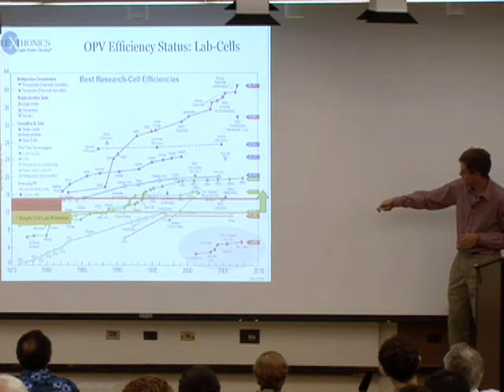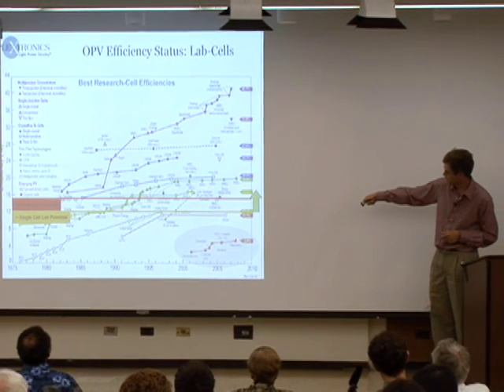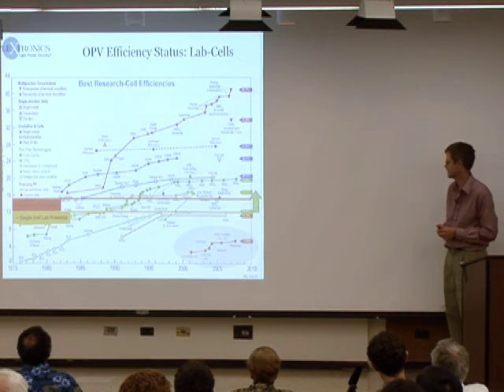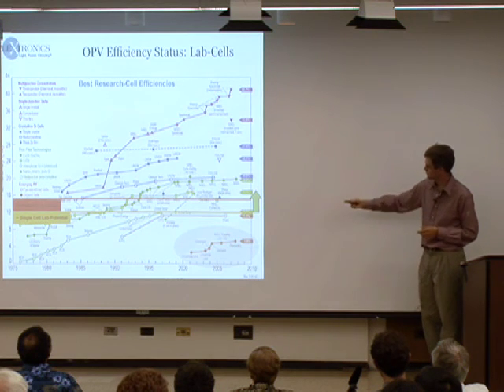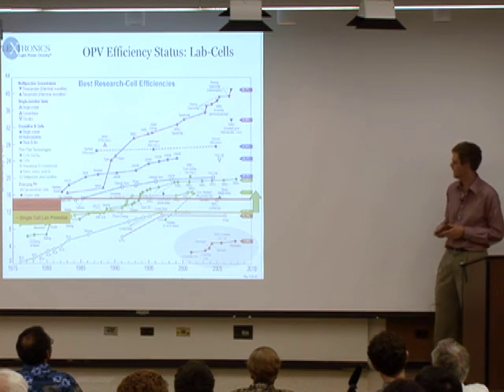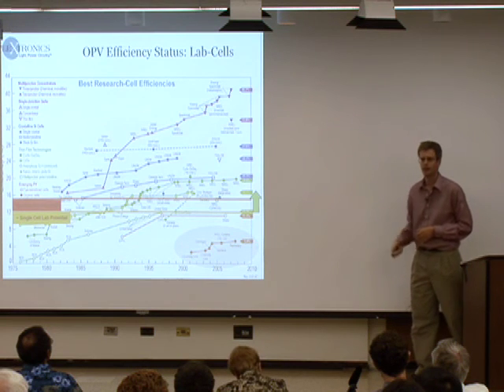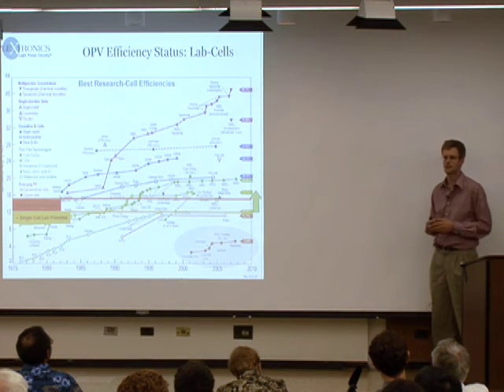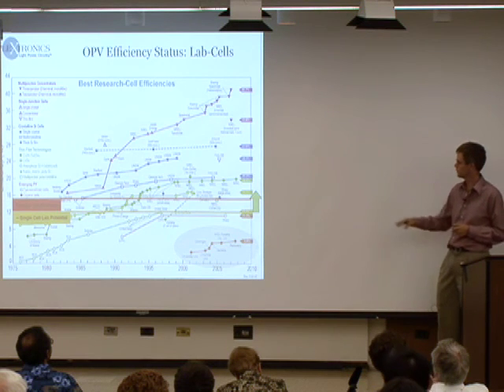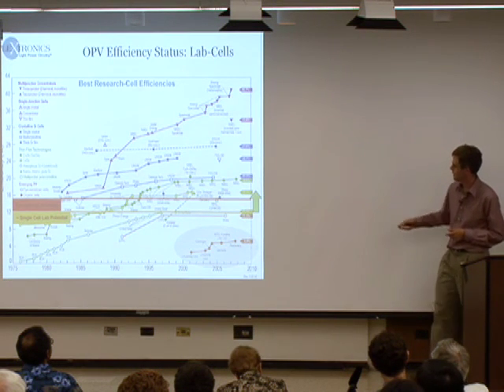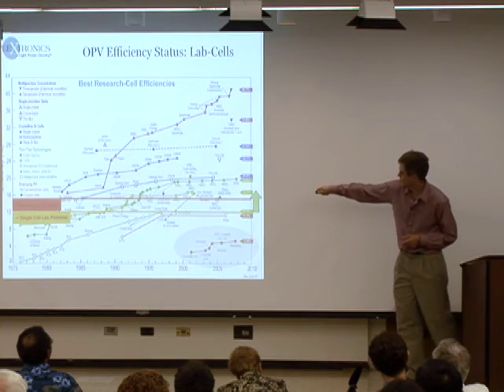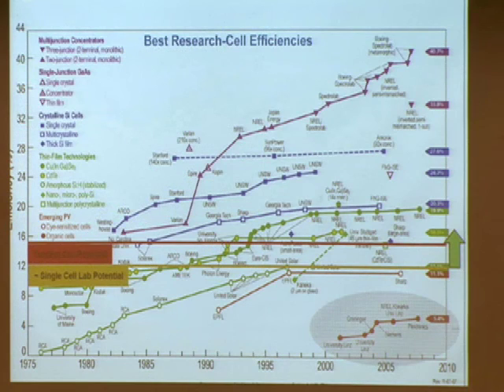So the organics, right now, the world record, on this plot it's shown as 5.4. Plextronics just moved that up to 6.2. So we're at about 6.2% right now. But it's a very new approach. And what I want to show you today is that we're developing an understanding of what holds that efficiency back. And we have plans to push up. We think with just one semiconductor, we can get up to almost 15%. And we think we can go above that by stacking layers that absorb different parts of the solar spectrum.